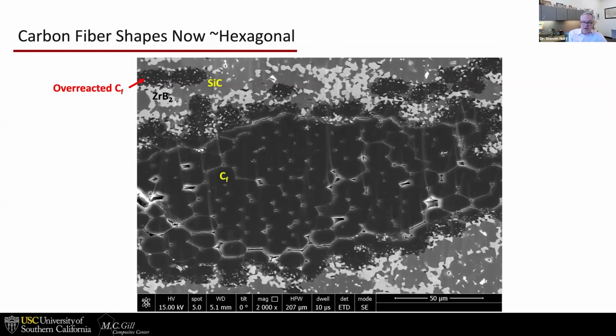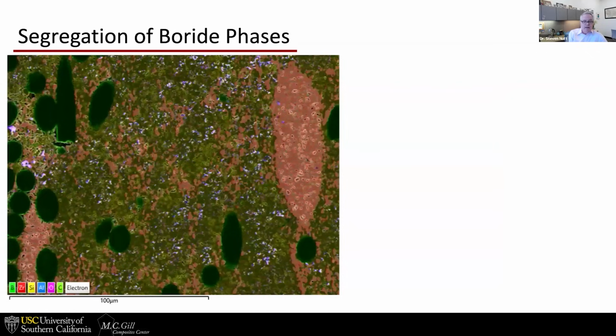Looking at the carbon fiber bundles, actually the fibers have sintered together. You can see they're no longer round, and in fact, they actually have some sort of faceted boundaries where they fused together. And then upper left, you can see that the fibers that are isolated by themselves have actually reacted with the matrix component. The bad actor here is zirconium diboride. It really attacks the carbon and reacts pretty strongly with it. That's not a showstopper necessarily for brake rotors.